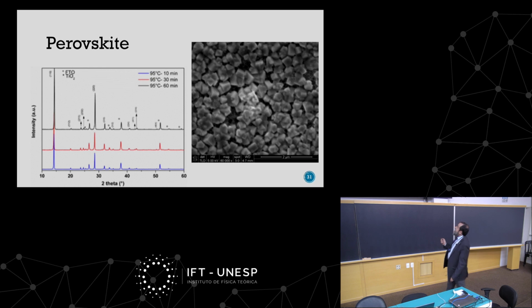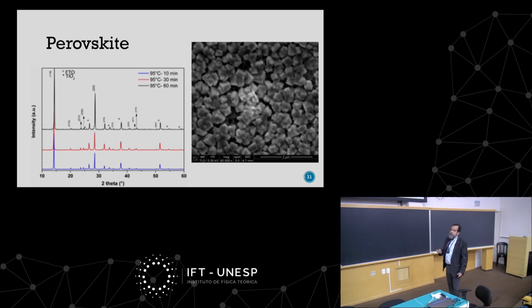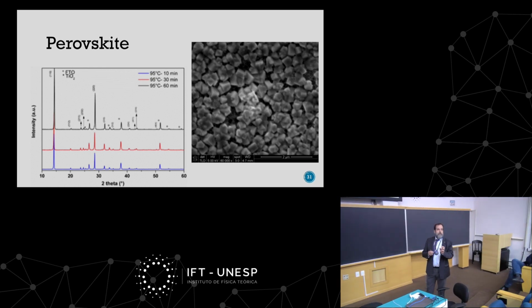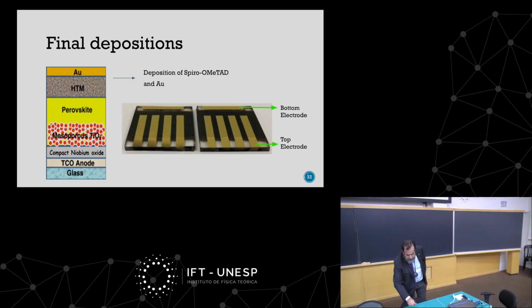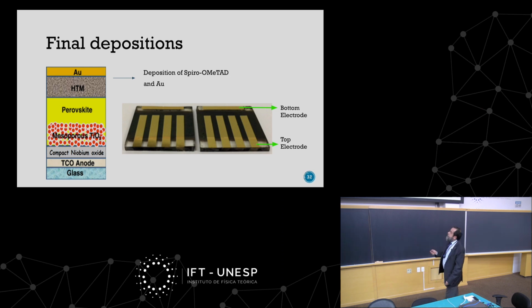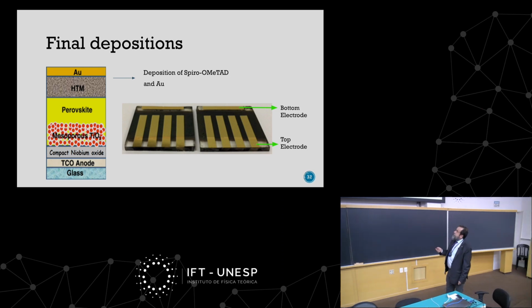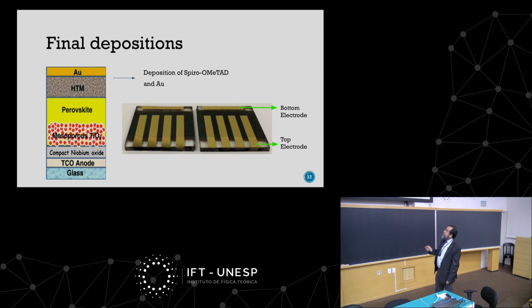So the perovskites, they do not form real single crystals. They are nanocrystals to microcrystals, depending on the parameters you produce. We can attest that by X-ray diffraction. And then finally, to finalize the structure, we deposit the spiro-OMeTAD and the gold.